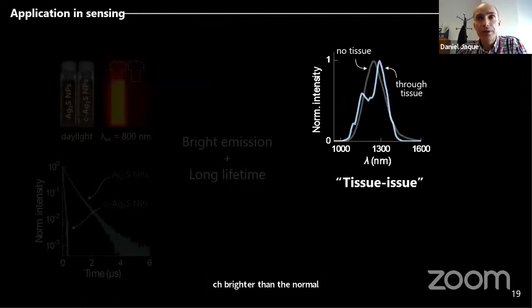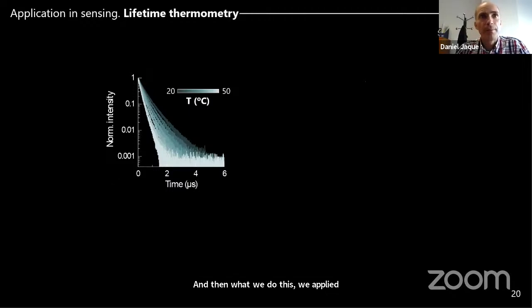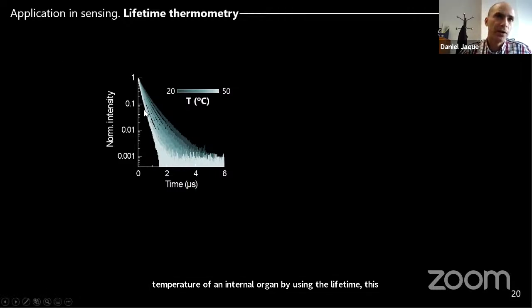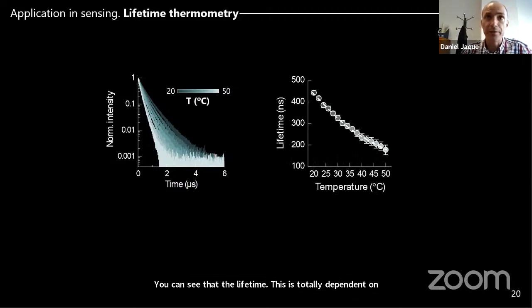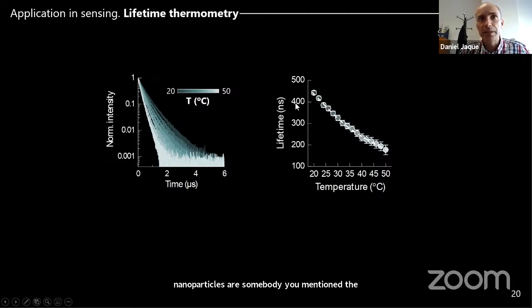Okay? And then what we do is we apply this to measure the temperature of an internal organ by using the lifetime. This is the fluorescent lifetime of these silver sulfide nanoparticles, obtained at different temperatures. You can see that the lifetime is strongly dependent on temperature. So if we measure the lifetime of these nanoparticles, we can know at which temperature the nanoparticles are. For example, if the luminescent lifetime is 400 nanoseconds, it means that your nanoparticle is at 22 degrees. If the fluorescent lifetime is 200 nanoseconds, it is 46 degrees.